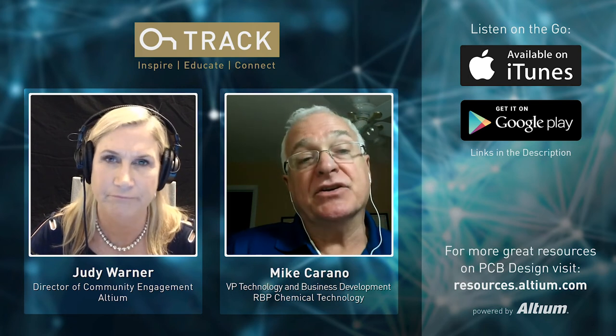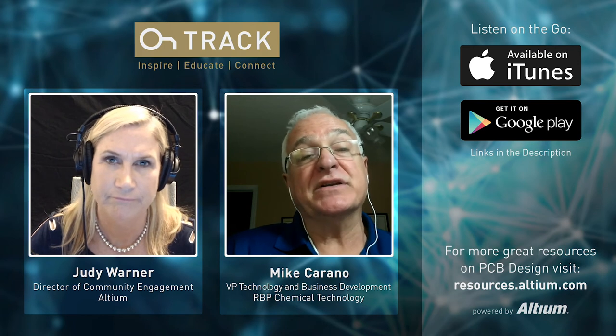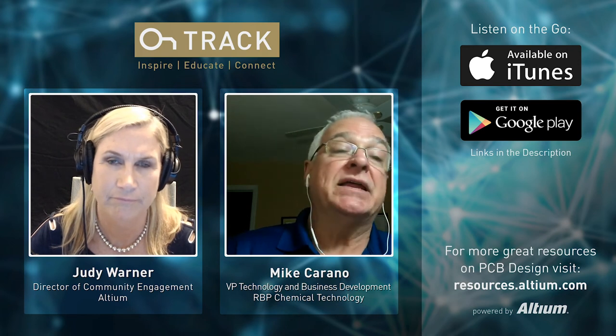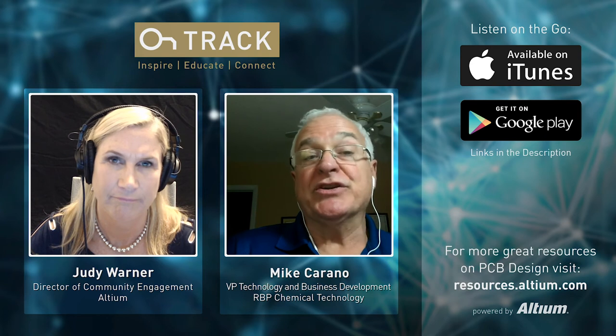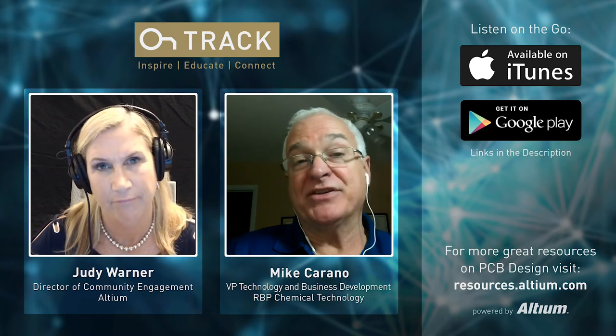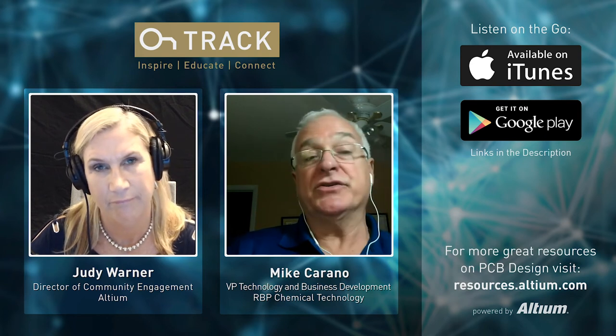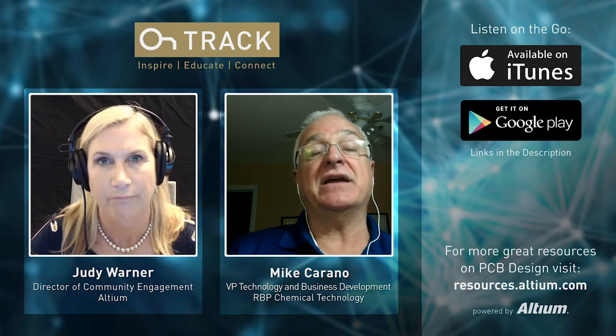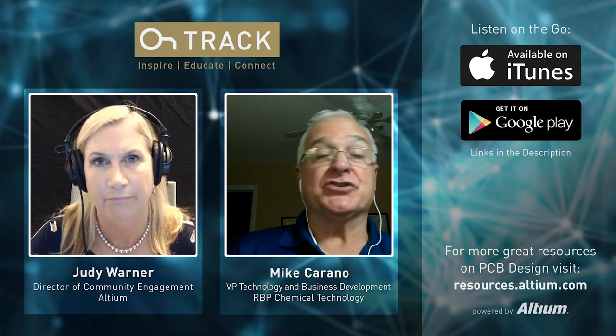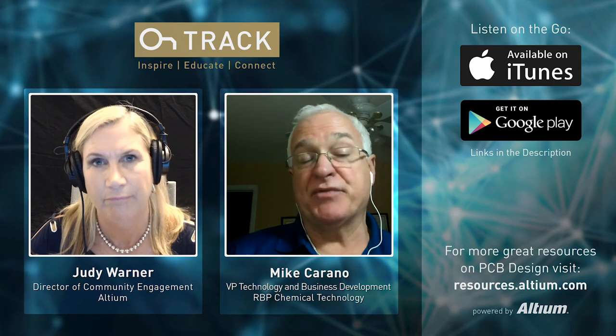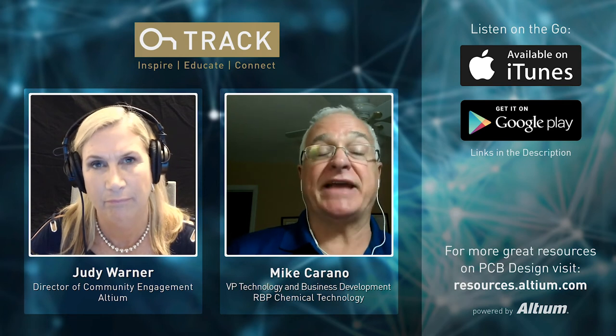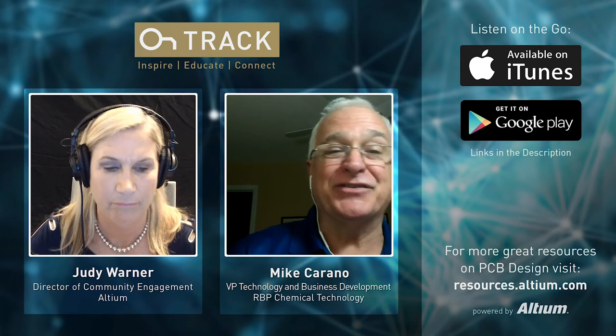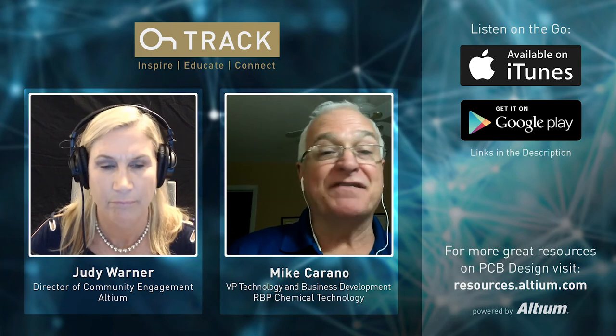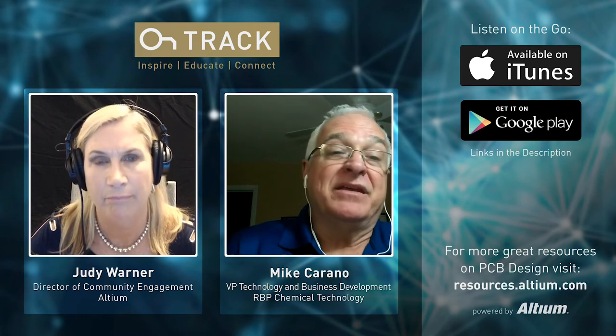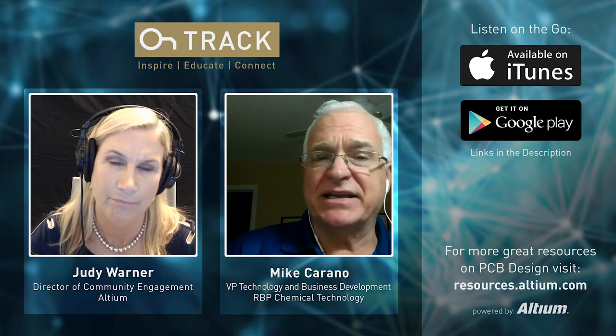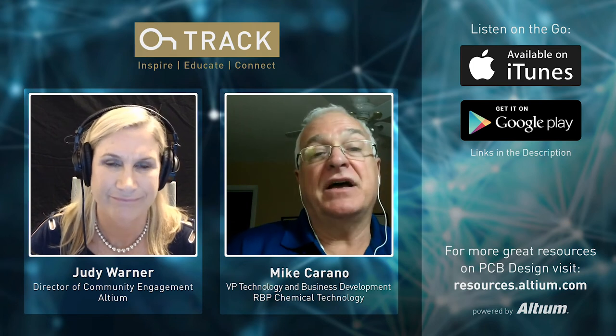Okay. Well, that's changed. Companies have made significant improvements in the reliability and also the ability of the OSP to reduce oxygen penetration on the copper. And that, again, is what you're trying to do. You're trying to prevent the underlying copper from oxidizing so that when the solder melts and spreads on the surface, it encapsulates the leads on the components and solidifies, and it's highly reliable. If the surface is oxidized even slightly and doesn't wet properly, you've lost your reliability.